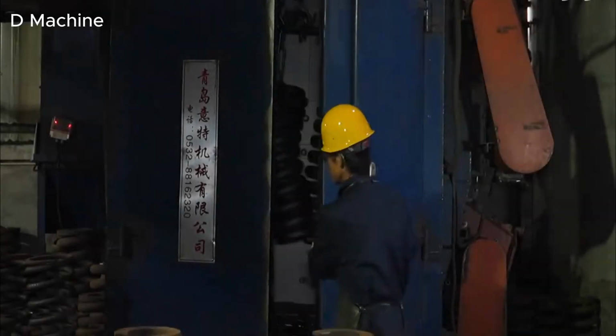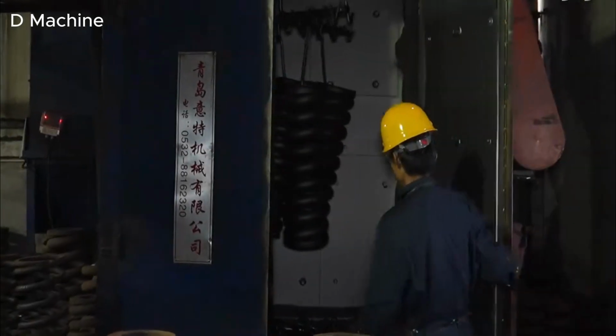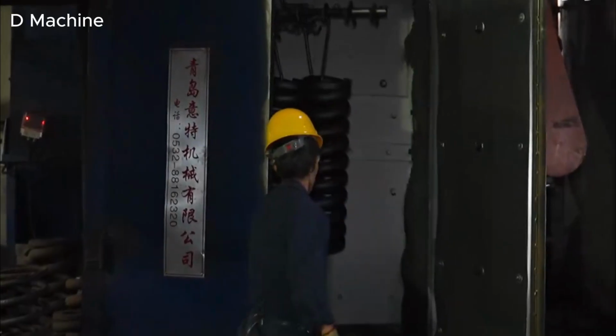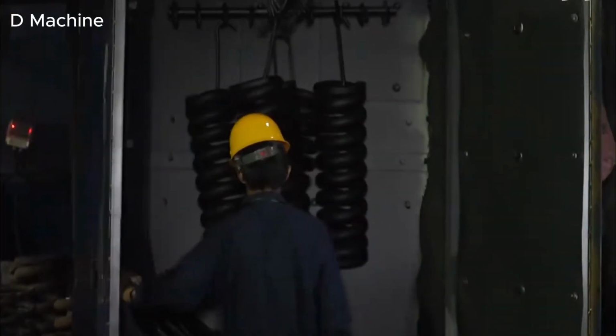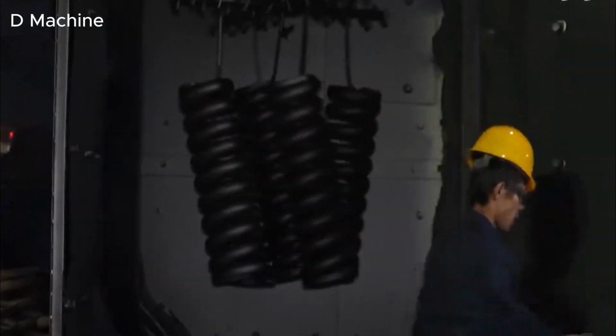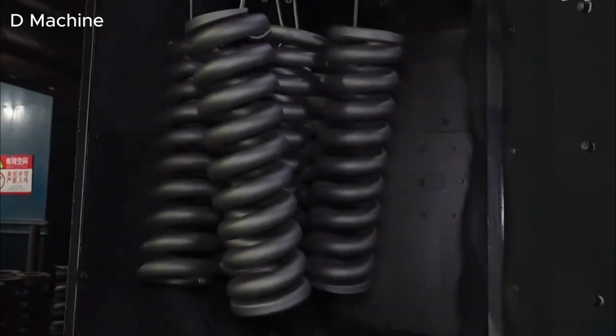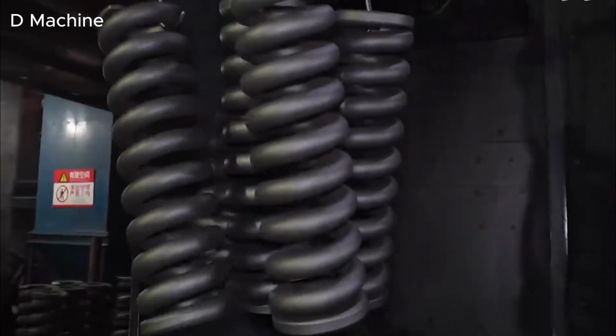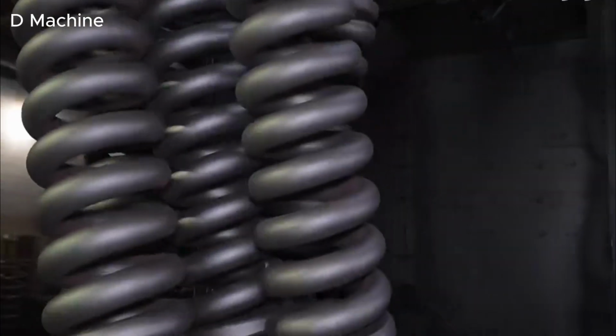More importantly, this process induces a layer of beneficial compressive stress on the surface, dramatically increasing fatigue life and helping the spring survive millions of load cycles. When the chamber doors open, the springs emerge darker, smoother, and with a strengthened surface, ready for final finishing.